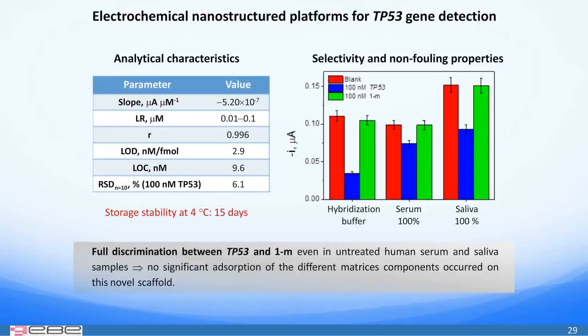Under the optimized working conditions, the analytical characteristics obtained for the synthetic target are summarized in the table. This platform allows a limit of detection of 2.9 femtomoles and demonstrates a 15 days storage stability at 4 degrees Celsius. The selectivity results show a complete discrimination between perfectly matched and single-base mismatched DNA.